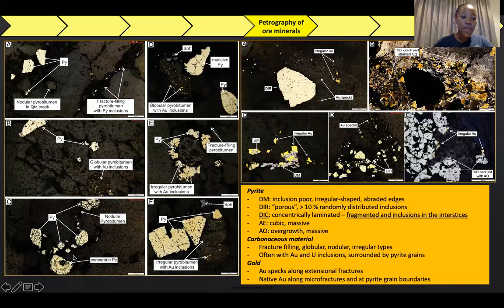The concentrically laminated detrital pyrites are the most important to distinguish because they consist of concentric sets of laminae, often with inclusions of gold in the interstices. Another important feature is that they are fractured, and this shows that they did not form in the Basal Reef, but were rather transported from a sedimentary precursor with their preserved internal structure indicating a short travel distance from their source while carrying trace elements and gold between their laminae.